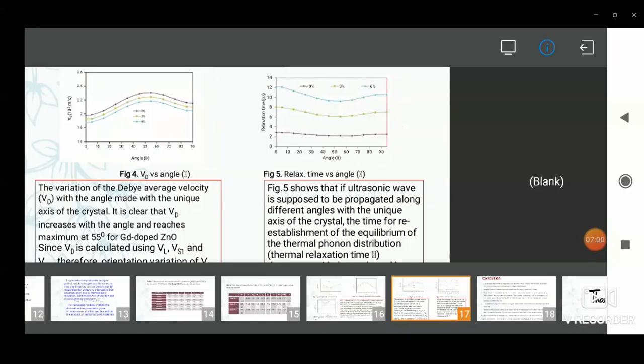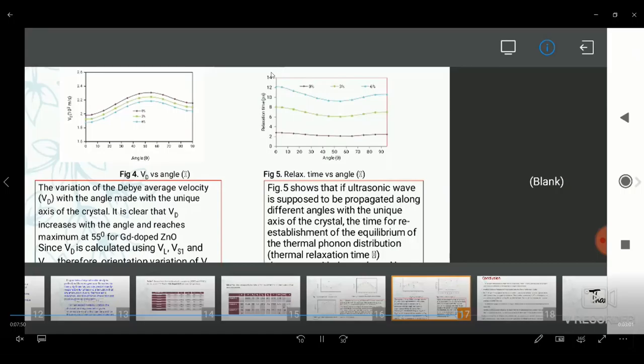Figure 4, Vd versus angle theta. Variation of the Debye average velocity Vd with the angle made with the unique axis of the crystal. It's clear that the Vd increases with the angle and reaches the maximum at 55 degrees for the Gd-doped zinc oxide. Since the Vd is calculated using VL, VS1, VS2, the orientation variation of the Vd follows that of VL, VS1, VS2. The maximum in the Vd at 55 degrees is due to the combined effect of VL, VS1 and VS2.